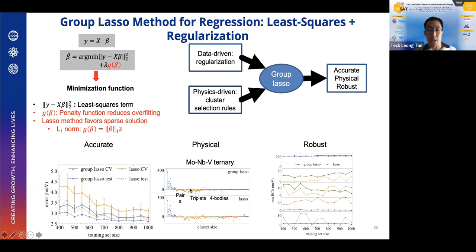We know that in material science, usually those interactions with the shortest distance will be the strongest, and further away interactions and multi-body interactions should be the weakest, right? So if we use group Lasso, we actually have this physics built in. You can see that the pair interactions are strong, the triplets fairly strong, but the 4-body and 5-body interactions are getting weaker and weaker, right?